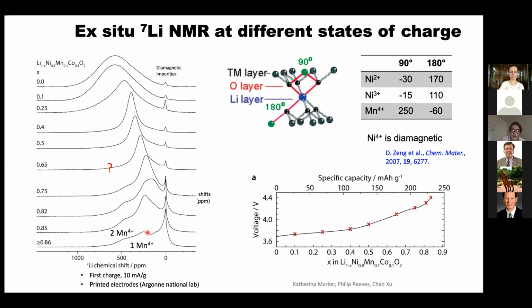And over years, we've worked out the whole language of how to explain these NMR spectra. And basically, you could look at this lithium and you can say what is in the first coordination shell and what is in the second coordination shell, and what shifts would you get from the interaction of a nickel or a manganese with the lithium. And at the top of charge, all of the nickel is nickel 4+. Nickel 4+ is diamagnetic, so it doesn't give you this shift called the hyperfine shift, but the manganese is the one that gives you the shift, and it has a large shift of about 250 ppm when you have this so-called 90-degree interaction. And so this resonance is due to one manganese, and this is due to two manganese in the local coordination shell. So we can get this exquisite level of information on local structure.